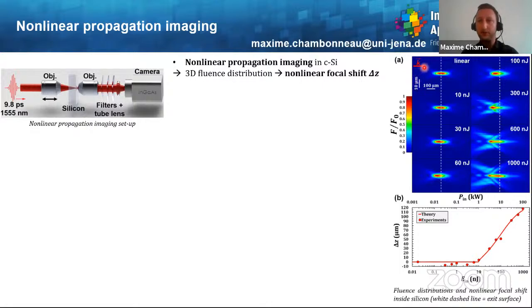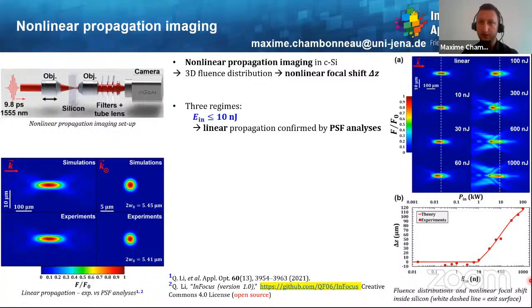And moreover, with this kind of data, we are able to measure the nonlinear focal shift as a function of the energy, which is depicted here at the bottom. So here on this data on the right, one can distinguish three different regimes. The first one is at very low input pulse energy, the linear propagation regime, which was somehow confirmed by some simulations that we carried out with the model which was developed recently by my colleague Qingfeng Li, which is open source and thus open access. And if you are interested in doing these kinds of simulations, please feel free to note those two references. This might be useful for many applications, actually.